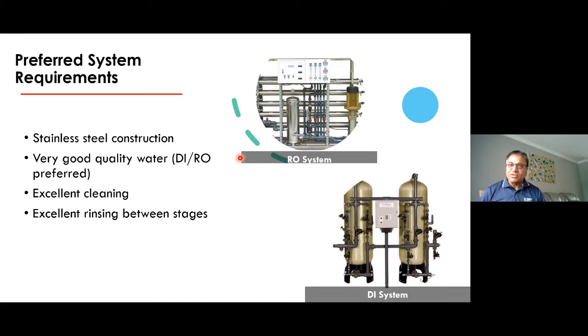In a cleaner coater version with iron phosphate, if you compromise a little bit on cleaning in your cleaner stage, iron phosphate will help with the extra cleaning. Zinc phosphate will help with the extra etching. That is not the case with the zirconium pretreatment whatsoever. So there is no ifs and buts about it. You have got to clean the parts quite well. Same thing applies with the rinsing. Excellent rinsing between the stages. And if you don't rinse the parts well, you might as well forget about what you are about to apply, which is a zirconium pretreatment.